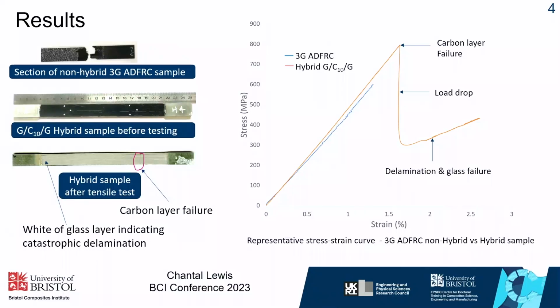So these are the results of the tensile test, and it confirms what was predicted, that the specimen design that was chosen failed in the desired failure region. You can see the sharp load drop where the carbon layer has failed. And as the test continues, the glass starts to delaminate as it carries the load from the testing. That's confirmed in the images on that side. You can see the black line in the gauge section of the specimen, which denotes the single fracture of the carbon layer, and then the change of color of the specimen from black to white indicates that the glass layers are starting to delaminate.